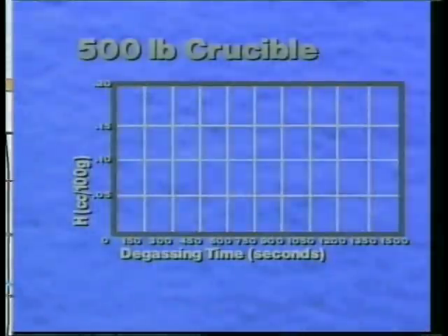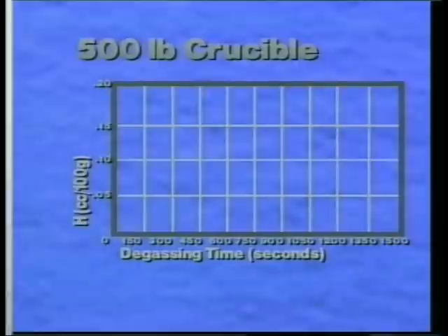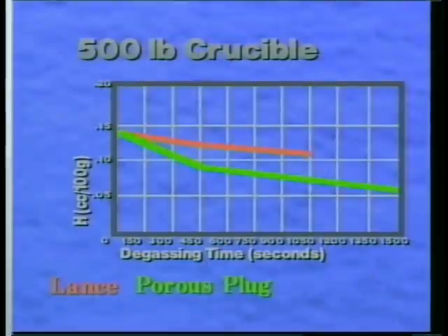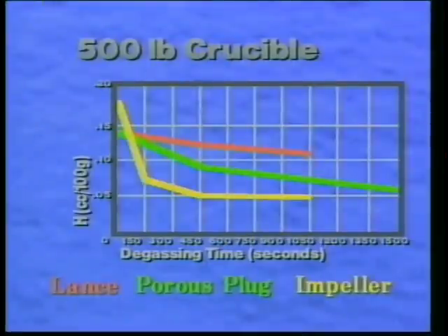Now, in the accompanying graph, we have three different fluxing methods depicted. What we're doing is showing hydrogen concentration as a function of time, and the data was generated by using a 500-pound laboratory melt by a colleague, Dr. Jeffrey Sigworth. In the first case, a lance was used to sparge an aluminum melt, followed by a porous plug, and then finally the rotary impeller degasser. And it's clear that the rotary impeller degasser is superior in terms of hydrogen removal than the other two methods.